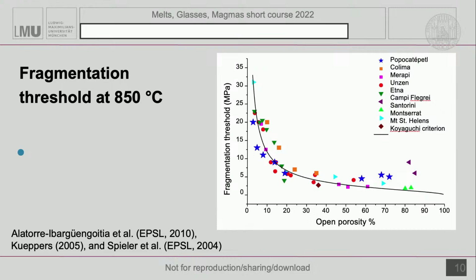And they go into the stage of polygonal foams and all kinds of things to avoid the geometric problem of having such high porosities. And you can see that the strength, or the threshold, drops from about 30 MPa to about 3 MPa, so about a factor of 10 in the tensile strength, from a solid rock with no vesicles all the way down to something you might use in the bathroom, a pumice for cleaning roughness away from your skin. Yeah? These stones which you can buy in a drugstore.